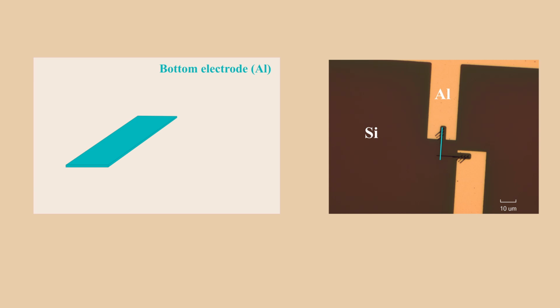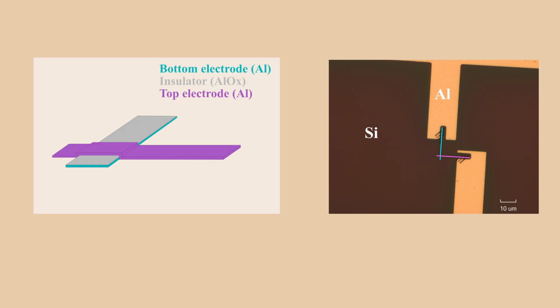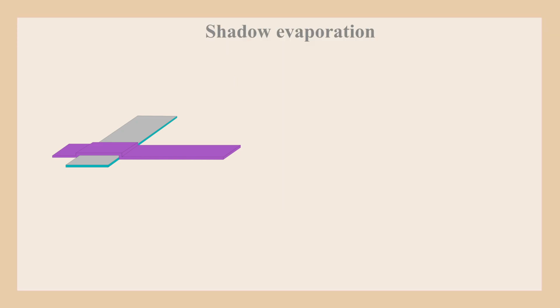Depositing the Josephson junctions will require us to get a bit clever, because 3 different depositions need to happen at 3 distinct places, but they need to happen one at a time. We need to first deposit the bottom electrode, then we need to grow the insulating oxide on top, then we need to deposit the second electrode, which will go over here, and only then we want to put the connecting patches on. The problem is that we already have all of these regions opened in the resist, so to be able to selectively deposit to only one of these regions at a time, we will use a trick called shadow evaporation. In this technique, we will deposit the metal from an angle as opposed to just straight from the top as we did before.